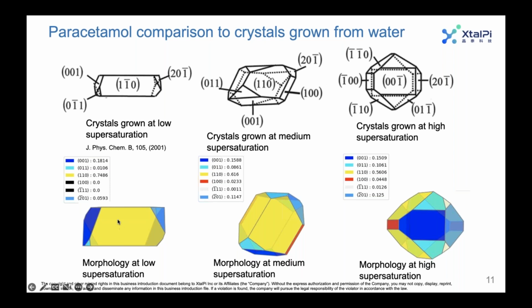Specifically, we see a more needle-like shape transforming to a more prismatic shape in the medium supersaturation, and then becoming even more prismatic, almost to the spherical end of things, in the high supersaturation. And the method is sensitive enough to capture those types of changes from the modeling.